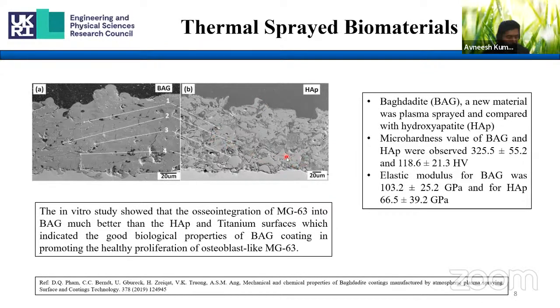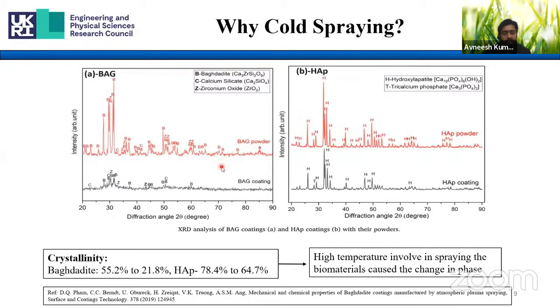This high temperature sometimes leads to a change in phase of these coatings. To see that, we went through their XRD results, and we found that before and after spraying, there was some change in phase in both the coatings, in hydroxyapatite and in baghdadite. They reported that the crystallinity of these coatings decreased after spraying. Before spraying, baghdadite had 55% crystallinity, and after coating, it was around 21%. Similarly, for hydroxyapatite, it was 78%, and after coating, around 64%. And they gave the same reason, the high temperature involved in plasma spraying.